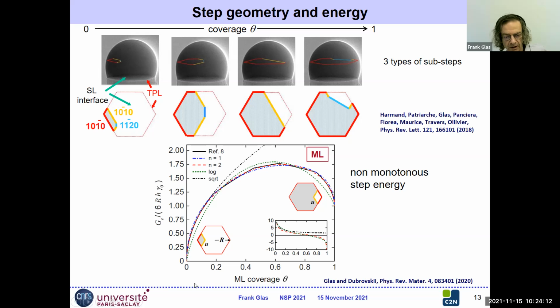The monolayer is restrained to the hexagonal top facet of the nanowire. Here we have a top view. And a complicating thing is that it's made of several segments which have different energy, segments in the liquid and segments at the triple phase line of the nanowire at the edge of the facet.